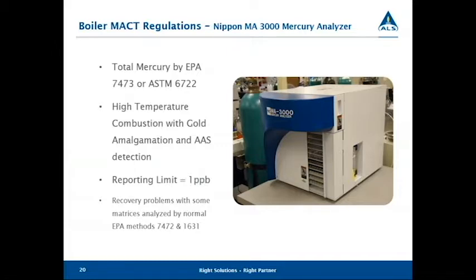What makes this method so good for the type of samples that we're analyzing is that the normal environmental methods are not able to get full recovery of the mercury that may be tied up in, say, the plastic or the rubber matrix of the sample. And so they're going to result in a low recovery of your mercury. Those methods include EPA 7472 and 1631. Now for wood chips and sludge and other easily digested samples, those methods work really well. But any samples that have plastics or rubber in them, the mercury really needs to be done by the combustion method.